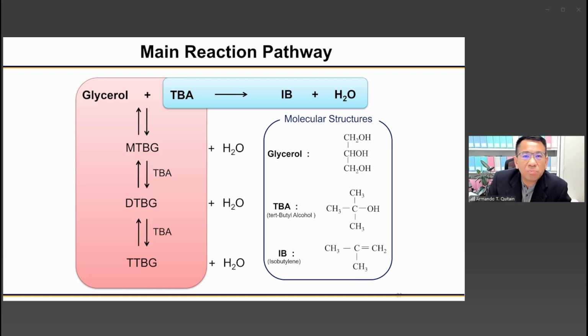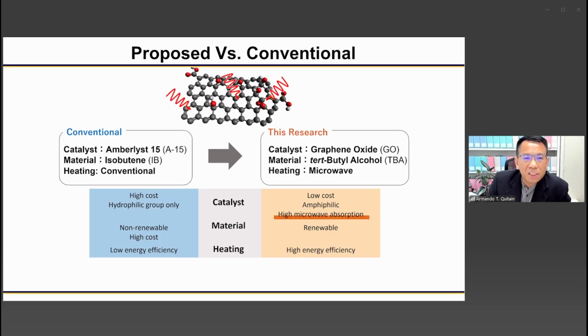So this is actually the main reaction pathway for the etherification of glycerol to produce MTBG, DTBG, and TTBG. There is a side reaction, which is the disadvantage of using TBA. TBA can be dehydrated to produce isobutene as well. And isobutene has a very low boiling point of -6 degrees centigrade. So after forming isobutene, it will evaporate and escape from the reaction zone. That's the problem with the use of tert-butyl alcohol. Anyway, we were successful in converting this glycerol by reacting with TBA in the presence of graphene oxide.